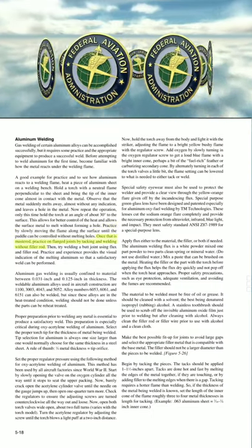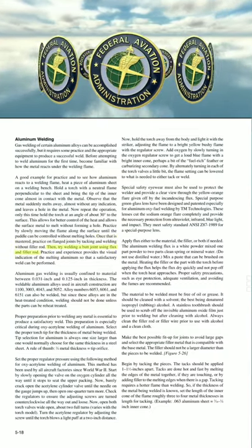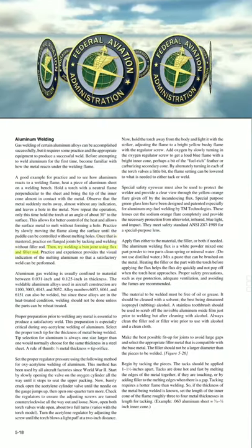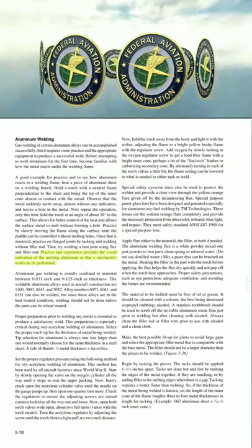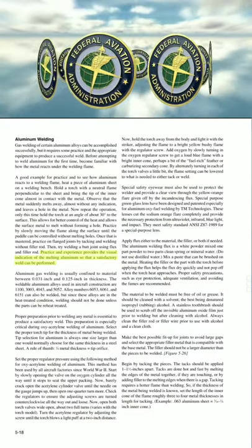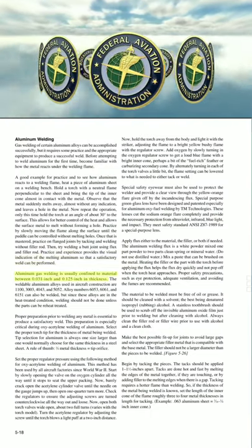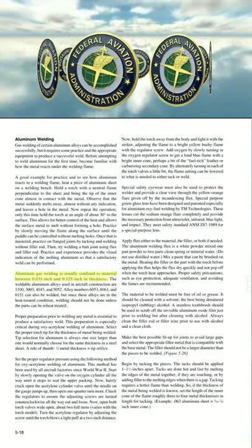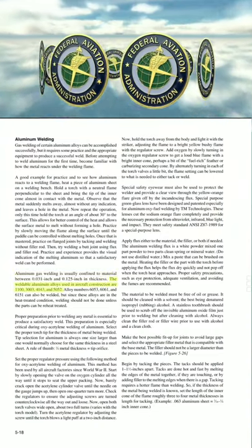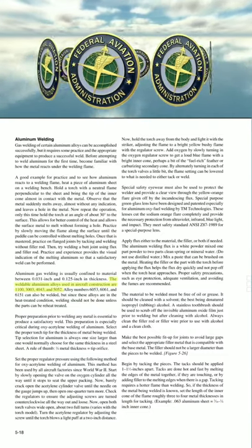Once that is mastered, practice on flanged joints by tacking and welding without filler rod. Then, try welding a butt joint using flux and filler rod. Practice and experience provides the visual indication of the melting aluminum, so that a satisfactory weld can be performed. Aluminum gas welding is usually confined to material between 0.031 inch and 0.125 inch in thickness. The weldable aluminum alloys used in aircraft construction are 1100, 3003, 4043, and 5052.